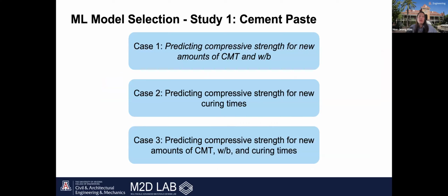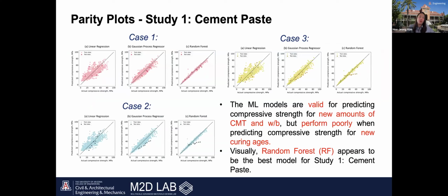And in study one, we tested three different cases to evaluate how well the machine learning models could predict new data, specifically new values of copper mine tailings content, water to binder ratio, and curing times. And in case one, the parity plot shows a strong agreement across all machine learning models, and the data points are evenly distributed around the black line, which represents the ideal condition where the predicted compressive strength equals the actual value. And this means that all the models were able to accurately predict the compressive strength of a cement paste with new amounts of copper mine tailings and water to binder ratio that were not included in the training data.